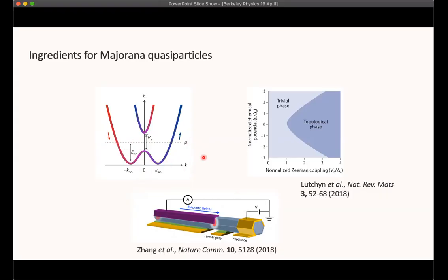Now, finally, we need superconductivity to get the elements of our one-dimensional chain of spinless fermions. And so we can introduce superconductivity by taking advantage of the proximity effect. We can bring in a relatively boring traditional superconductor, like the purple here is meant to show an aluminum layer that we've placed on our nanowire. And the proximity effect is what allows a superconductor in proximity to some other material to introduce superconductivity into that material. So what you end up getting is Cooper pairs in the semiconducting nanowire. And now you have a pairing gap that opens up on either side here at the